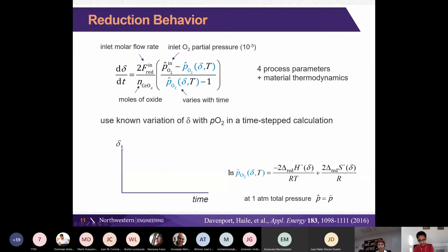So here we are. We're going to calculate the non-stoichiometry as a function of time. We have some input starting value of non-stoichiometry. That would be our equilibration, for example, with the steam that did the oxidation of the material. And this term here simply is the slope of the non-stoichiometry with time. So we calculate the slope, we input a time step. So here's our time step, and we use that to calculate the new value of the non-stoichiometry for a given increment. So we can set this as big or small as we want in our calculation so that we can calculate this profile.